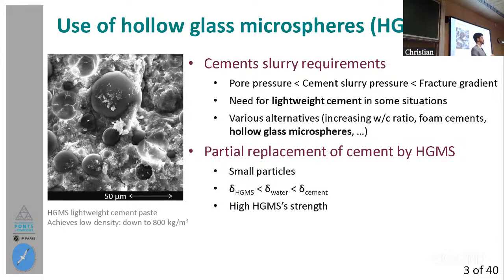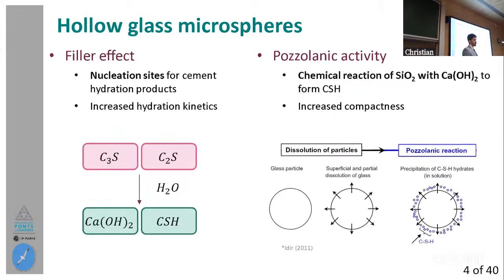So we are choosing in this research work to replace cement partially with hollow glass microspheres, which is a lightweight material. What are the main properties of this material? Well, they consist of small particles, they have a very low density, and they also have high strength. So many good properties. But since we are replacing cement partially with the spheres, we have to know what influence this sphere may have on the cement paste. For this purpose, I'm going to focus on two main aspects, which are the filler effect and the pozzolanic activity.